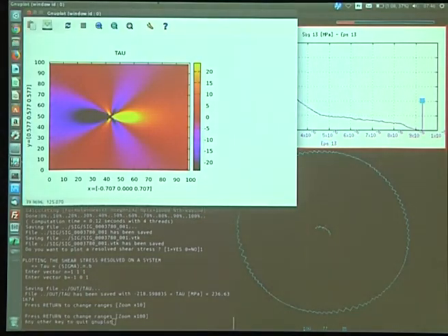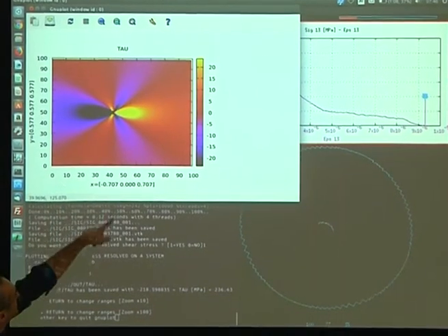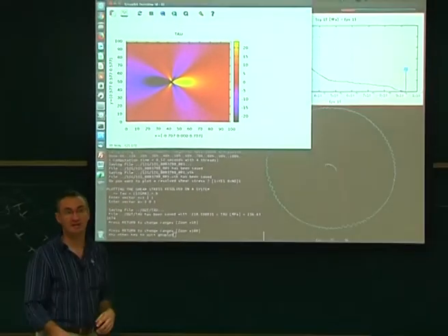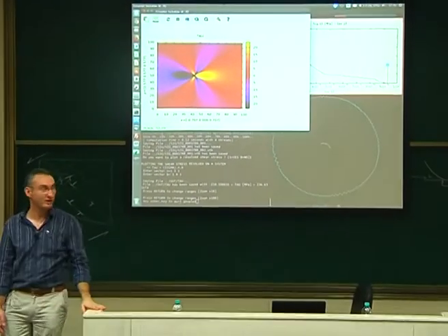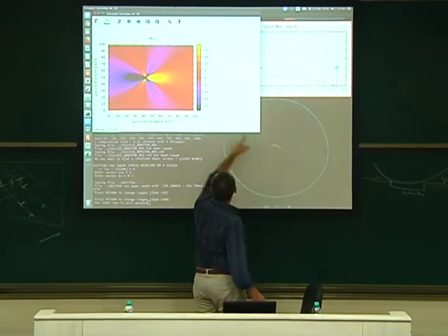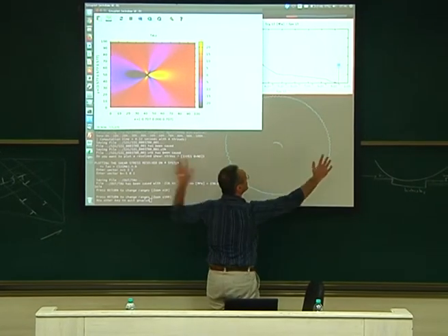So here you recognize the stress field of the dislocation. You see? So my dislocation is exactly there, and you can see the stress contour of your dislocation line, the positive, negative. All that I gave you in the textbook is here. This is for the edge. Okay? In that small plane here, this is the stress field which is acting in that plane. So with that, you can make an analysis in a bigger size zone.